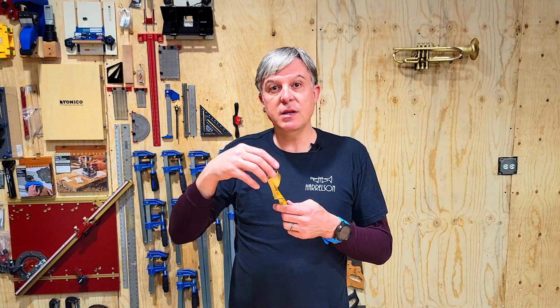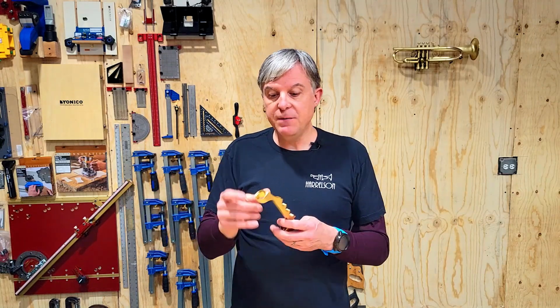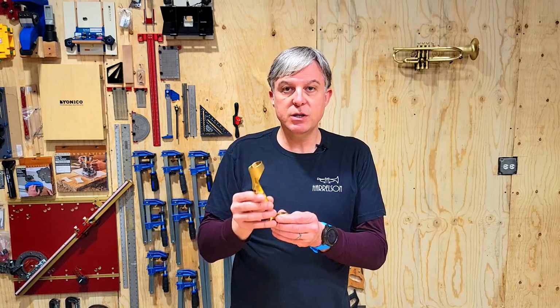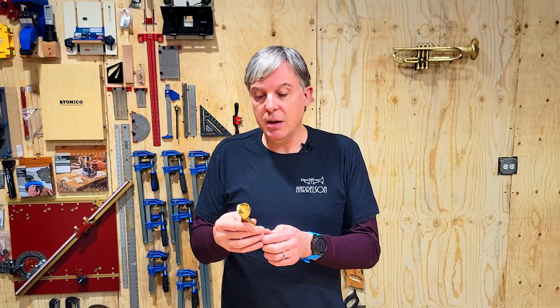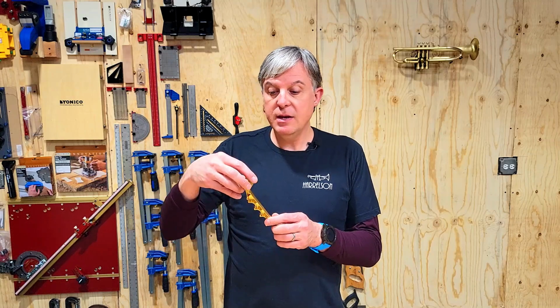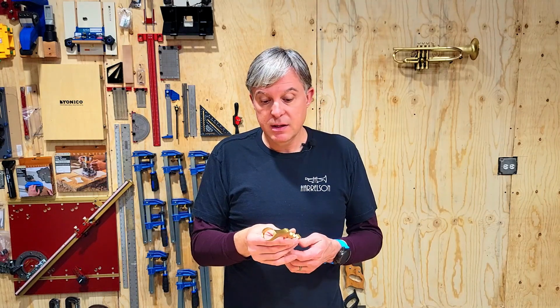And the best way to prevent that is to use a smaller end mill that creates less energy in the material to prevent having so many harmonics or so much energy in them. And that smaller end mill has to spin then at a higher rate. So in other words, if I were to cut this with a 10,000 RPM end mill, I could probably go down to maybe a 1/4 of an inch or even an 1/8 of an inch, although I'm not getting the most efficiency out of that 1/8 inch end mill. And at that point, that end mill could start to set this into vibration. Our machine that we used to make this actually went up to 80,000. So if I bumped that 1/8 inch end mill up to 20 or 30,000 RPM, then it could create those frequencies. There'd be enough energy to cause catastrophic failure, really.